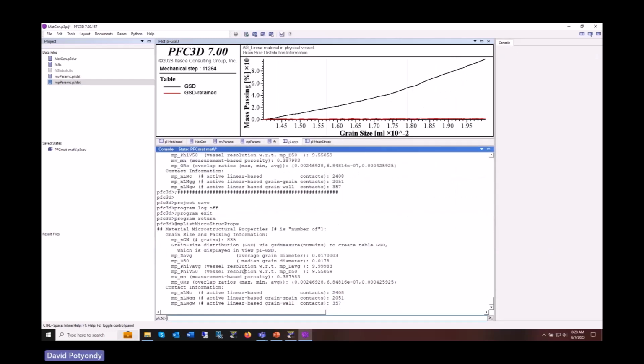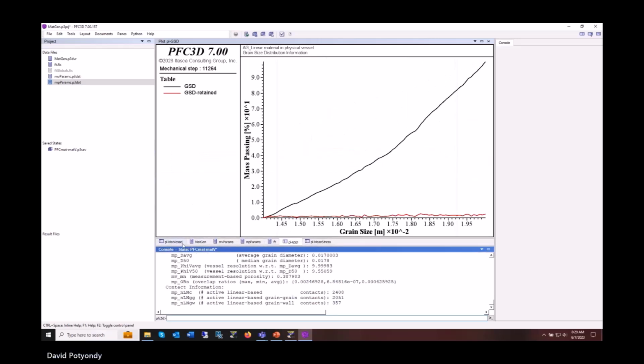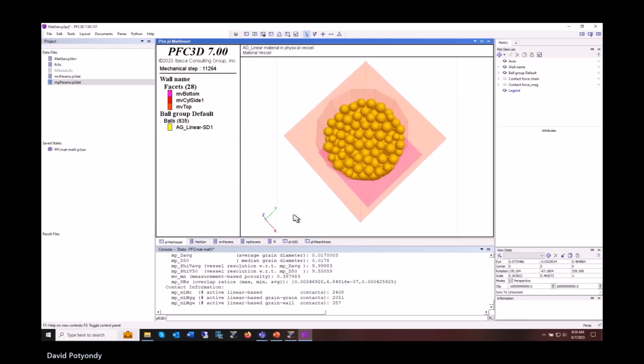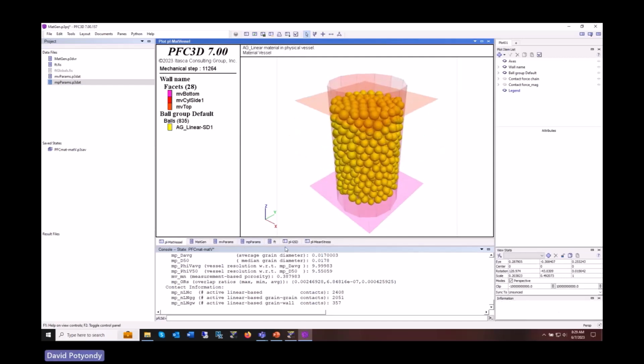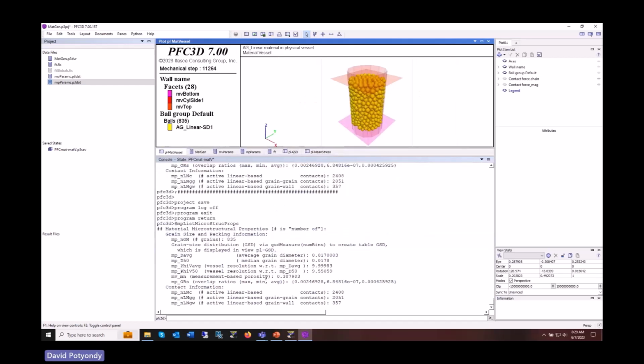What else is in the microstructural properties? Average grain diameter, 17 millimeters. Median grain diameter, which is the value at the D50 point of the size curve. Vessel resolution: given the average diameter, if we take the width of the vessel divided by the diameter, how many grains across? About 10. There's about 10 grains across here. That's always an important parameter in these types of systems. You want to know that. Measurement-based porosity, there we go: 0.388. That's from the measurement sphere coming back.